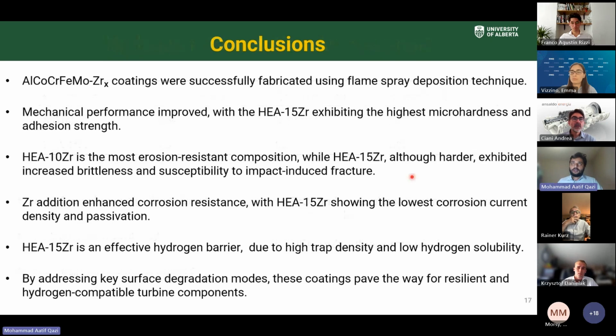Coming to the conclusion from the study, so we were able to fabricate AlCoCrFeMo coatings using flame spray. We saw an improvement in the mechanical performance with the HEA15 Zr exhibiting the highest micro hardness and adhesion strength. HEA10 Zr is the most erosion resistant composition. Zr addition enhanced corrosion resistance with HEA15 Zr showing the lowest corrosion rate. And then HEA15 Zr is an effective hydrogen barrier.